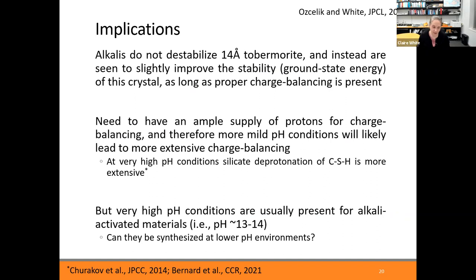If you have a sodium containing gel, you can get a gel that probably will perform in a similar manner to CSH gel, so long as you have hydroxylated regions within the material. What I mean by that is having the hydrogens present that are bonded to oxygens. So you need to have an ample supply of protons for charge balancing to form these hydroxyl units. However, in concrete, I haven't mentioned this yet, but the pH is quite high internally. It's about 12.5 or 13. So the higher the pH, the fewer protons you have. And this means that you're more unlikely to have this charge balancing that could occur.